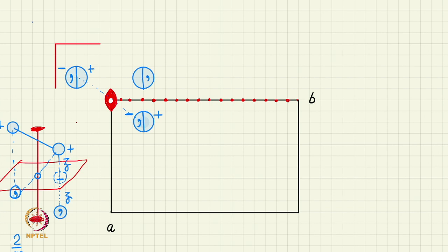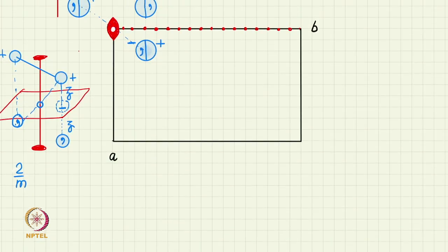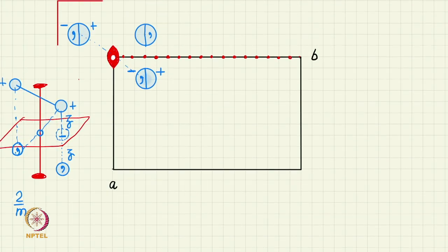And you can see that if something is at z and I translate it further c/2, it will go from z to z plus half, or we can write it as half plus z. So, just like for plus z we use the shortcut of writing only plus, similarly for half plus z we will use the shortcut of writing just half plus.